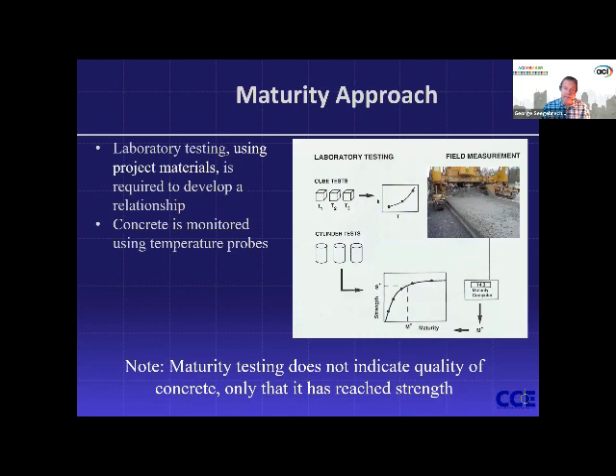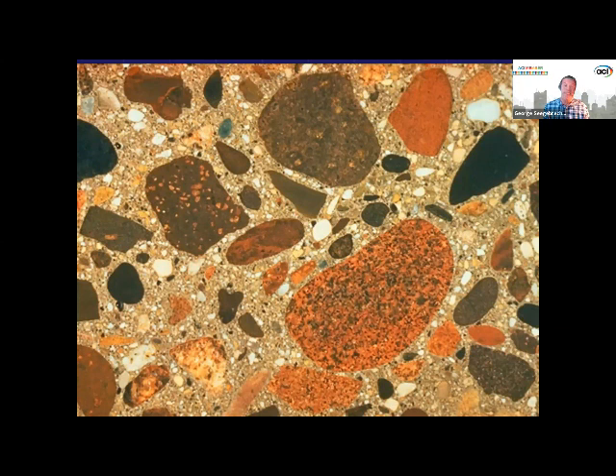And it is a laboratory test. So the cool thing is, once you have the maturity relationship established, you get the temperature history out in the field, and you can relate that back to your exact same material strength development history that you developed in the lab. Now you have to use the exact same material, and the downside of the maturity is if you change the mix proportions, then you have to redo your maturity relationship. So it is valuable. It is specific though.